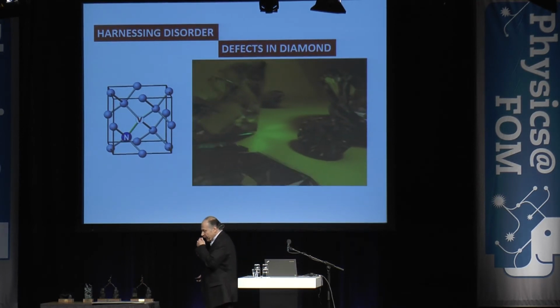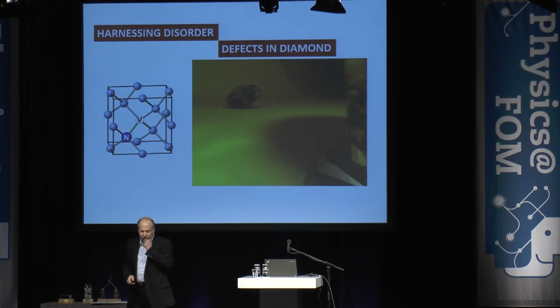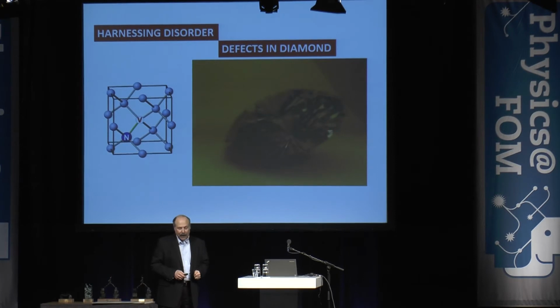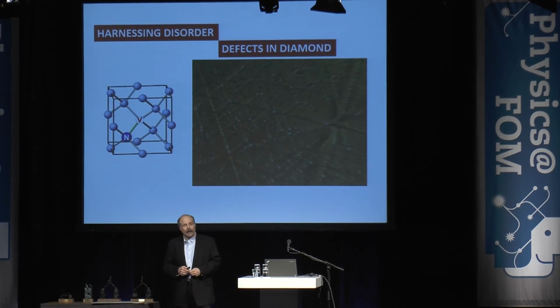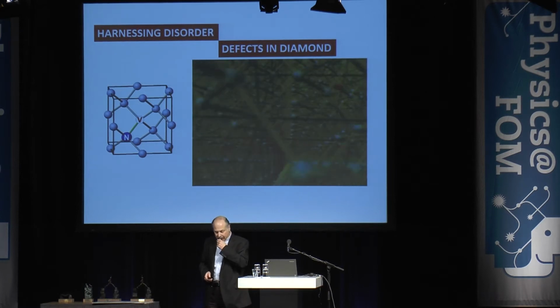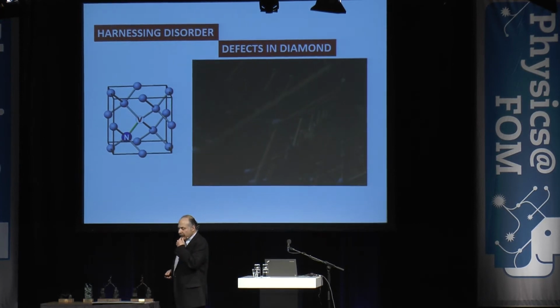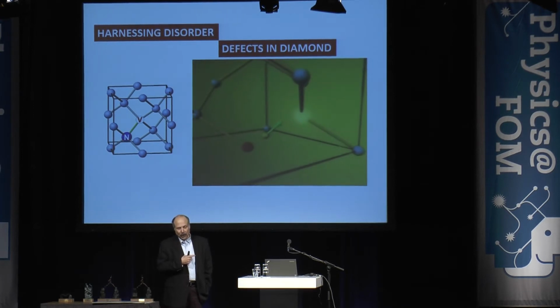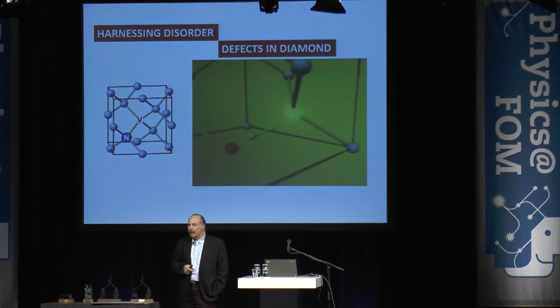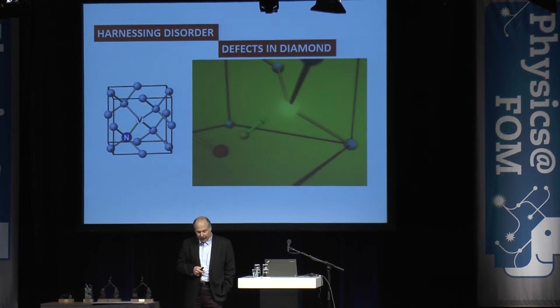So you take a diamond, either a natural diamond or one that you grow synthetically, and you start to look inside the diamond for defects. If you look inside a diamond, we know diamond is made of carbon, which you can see here in blue, in a very nice lattice. There can be some impurities in it, which are shown here in red. And once in a while, you'll have a missing carbon atom or a vacancy, which you can see here sort of glowing in white, which is near one of these dopants, in this case nitrogen in red.